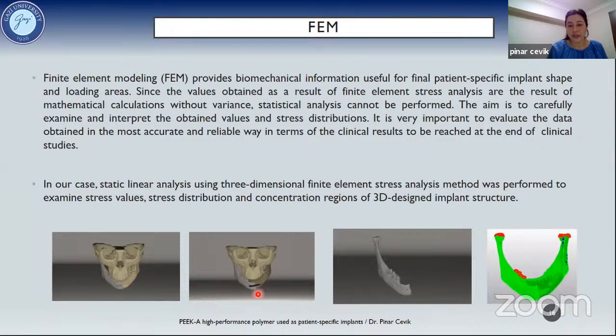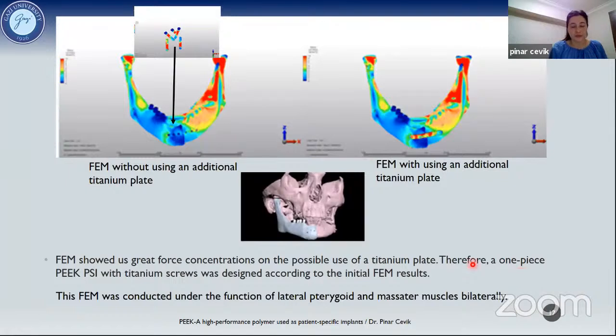First, we designed an additional titanium plate at the anterior side for the patient. At the left side, you can see no titanium plate, and the mandibular implant fabricated from PEEK and the finite element model. At the right side, you can see the FEM using an additional titanium plate. As seen at the right side, stress concentrations were high on the titanium plate. So we didn't use any additional titanium plate on the anterior side.